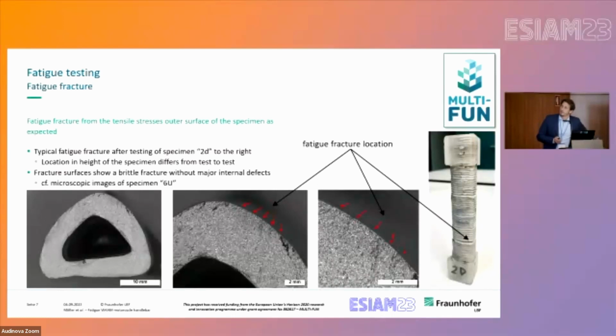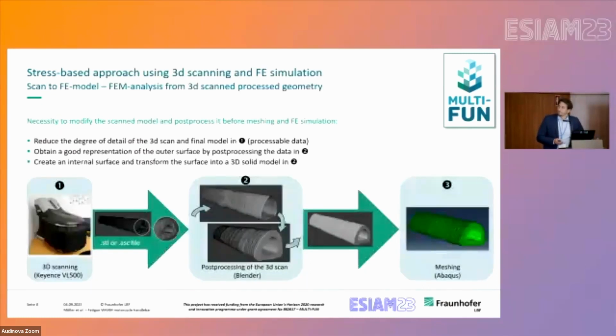Fracture locations are at the region of the highest stresses. So this is the inner part here of the specimen where these cracks then occur, propagating more or less from the outer surface to the inner part of the specimen. There are not so many internal defects, so it is reasonable that crack initiation is from the outer surface, which is not milled or something. So it's the surface as built from the WAAM process.